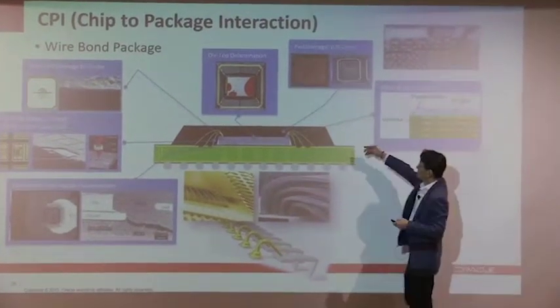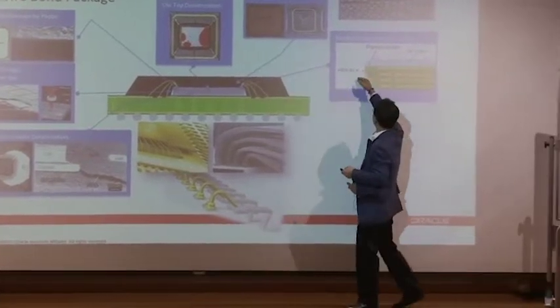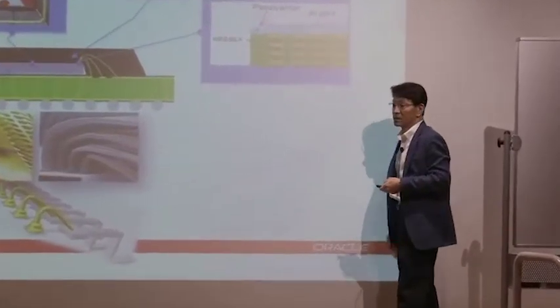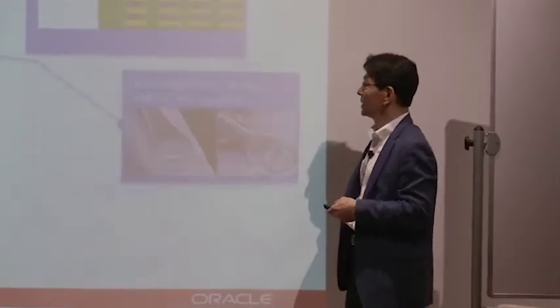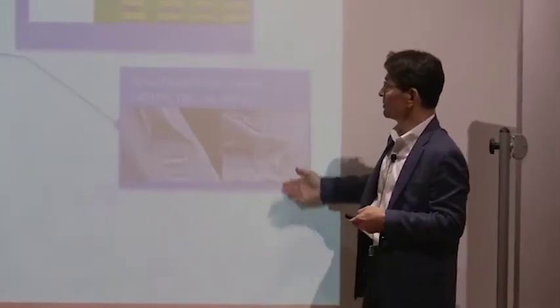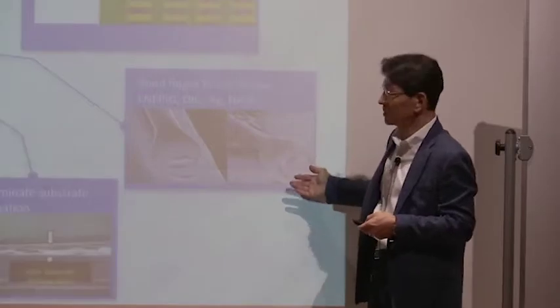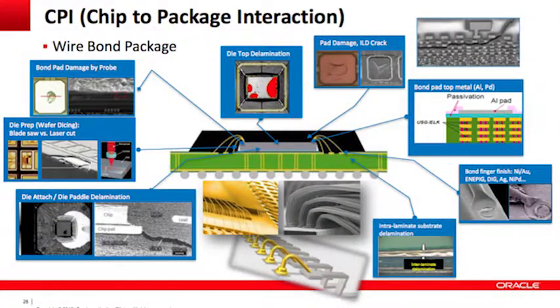And stress goes into the silicon inside, and creates ultra low-K delamination, and then the typical second-stage issue, substrate delamination. So this whole area is the responsibility of the packaging technology engineer to look at, to prevent ahead of time. When it happens, it's too late. We have to hold the line, shut down, fix the problem and then release it, and we lose money.